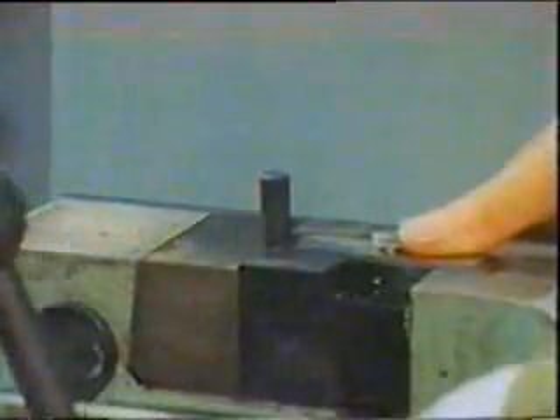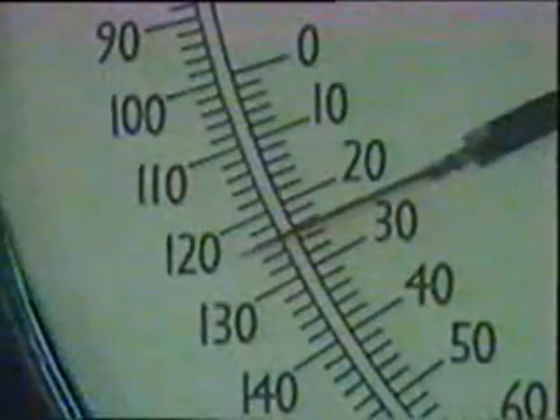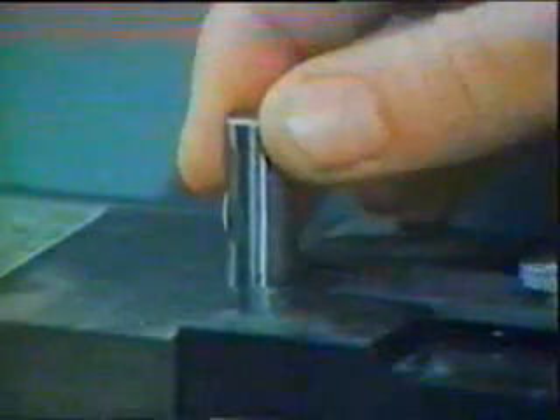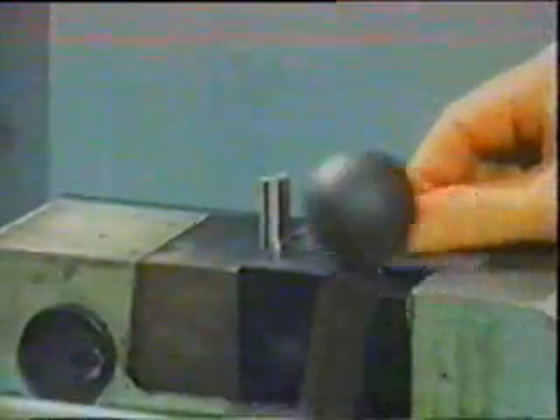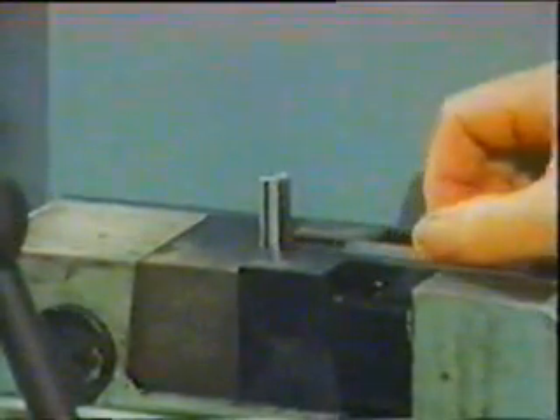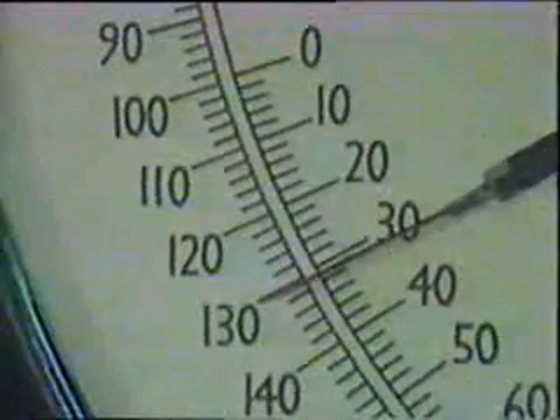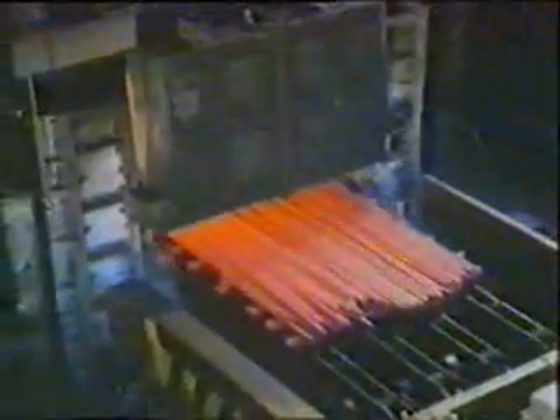Let's compare the toughness of a piece of forged steel before and after normalizing. Here's a piece of forged steel that's been specially prepared for the test. Now, toughness is the ability of a material to withstand shock loading or impact. That had a toughness value of 25 units. Now for the normalized piece of steel. For comparison, the test must be exactly the same. That had a toughness value of about 30 units. Normalizing has increased the toughness of the steel.